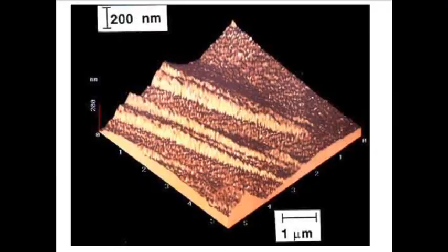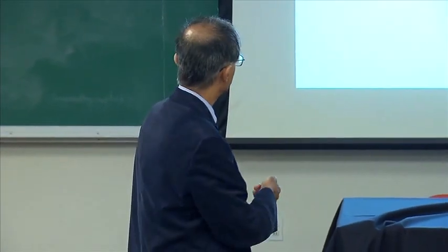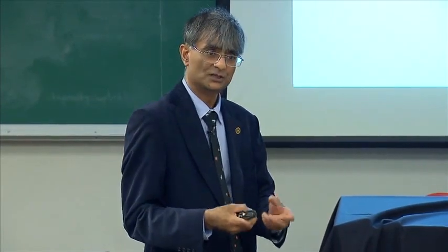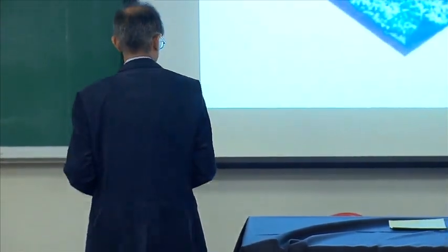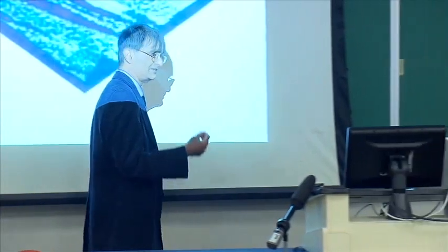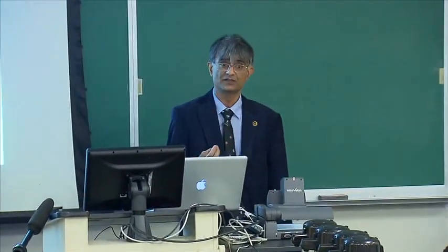And the second thing about this bainite reaction is that there is a shape deformation. So this is an atomic force microscope image where you take a crystal of austenite, you polish it completely flat, and then you allow it to transform into bainite. Then you get these massive deformations, which are good for work hardening. And work hardening prevents plastic instability. Okay? So these are called TRIP-assisted steels because the amount of austenite is quite small. It's about 15%. And it's produced by this partitioning of carbon.